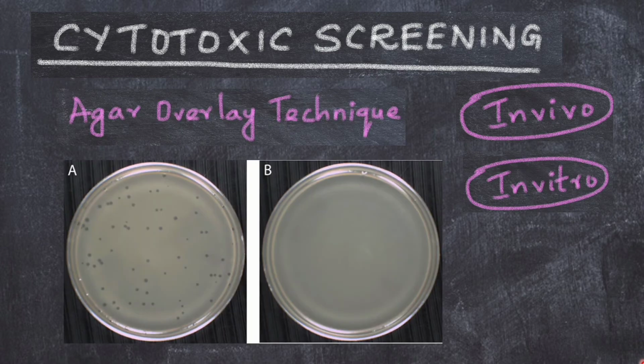So the material will be incubated with the cultured cells, and you look at these live cells at the end of the technique. One of the most commonly followed procedures is going to be the agar overlay technique, wherein the agar is spread over a layer of the cultured cells in the culture plate, and then it is going to be incubated with that particular dental material. If it is a safe material, it will be like in picture B, wherein no lysis is seen. It's going to be a clear culture. Whereas if the material is toxic, it will be as in picture A, wherein you can see numerous areas of clear zone of dead cells.